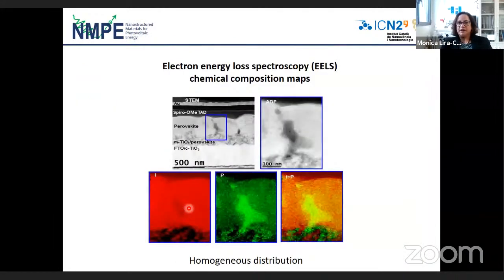Then we also analyzed by electron energy loss spectroscopy, just to see where our material is. Our additive has a phosphorus, so you can see where the phosphorus is, and you have an idea if it's only at the interfaces and the grain boundaries, or where it is. We observe a very homogeneous distribution of this phosphorus in the whole device, meaning that the additive is well distributed, even within these grain boundaries that you see here.